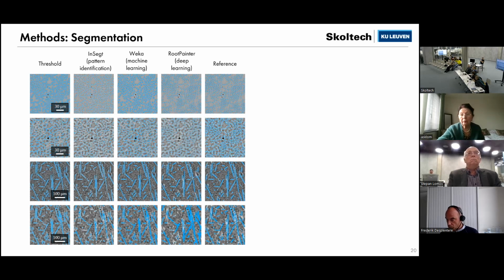But in reality, it's possible to have 40, even 50%, because the fibers will condense to each other very closely and they will be curved around each other. And it's very difficult to make it using parametric models. And this is why there is a development of image-based simulation, where we take the image of our material and find our objects. And after that, using these objects, we create our models. And also, of course, we can do something in between.